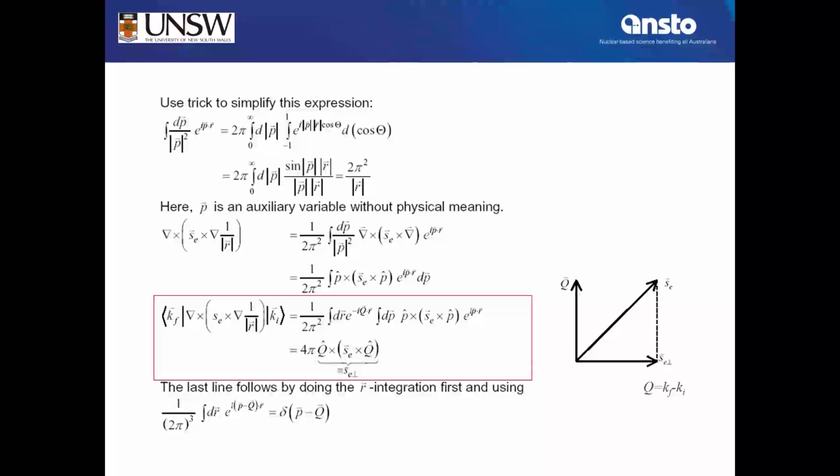If you now rotate the crystal in all possible directions and measure the spin component from all Bragg peaks from all the different directions, or one peak, it would be 6 in total, then you can directly calculate the precise spin direction and the magnitude of the magnetic moment.